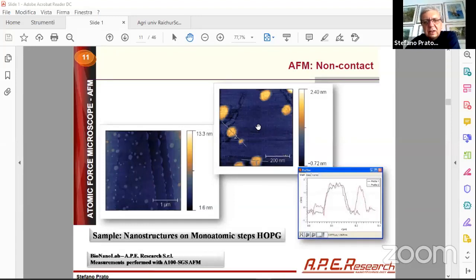This top part is a zoom of this part here. You can see the long lines, those are stripes that belong to the substrate, to the graphite. On top you have those islands, which are quite nice. They are more or less around the same size, and they are 1.5 nanometers tall. Those are not spherical, but like small terraces, a little bit hexagonal in shape. It means that they should have some kind of internal organization, and they're quite flat.